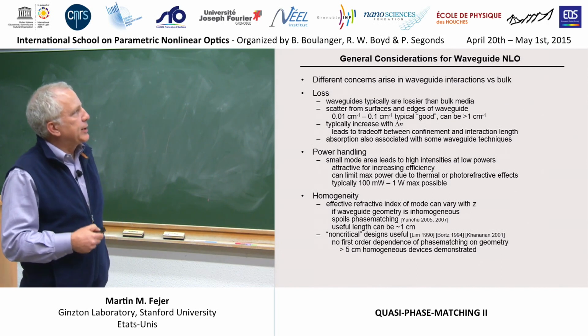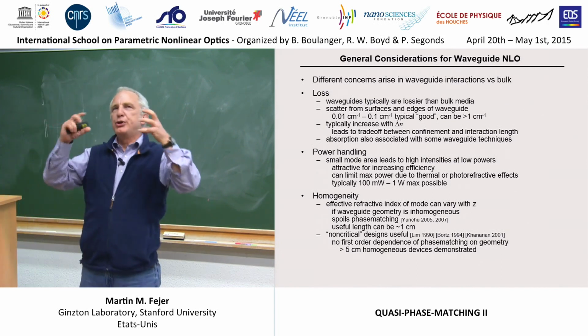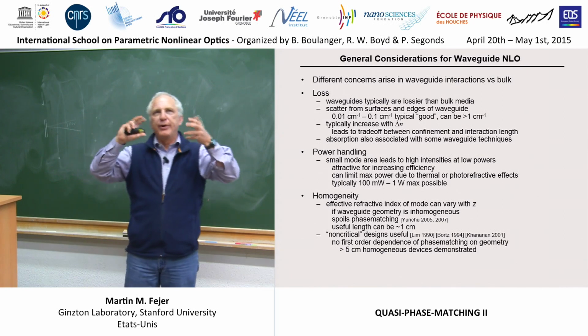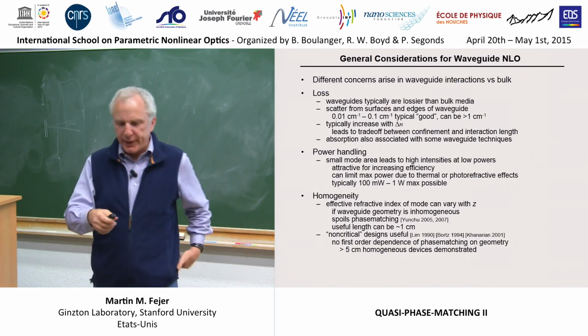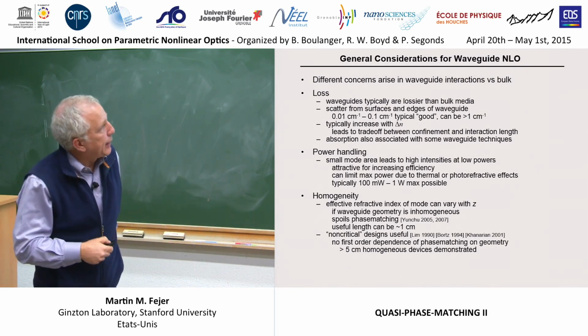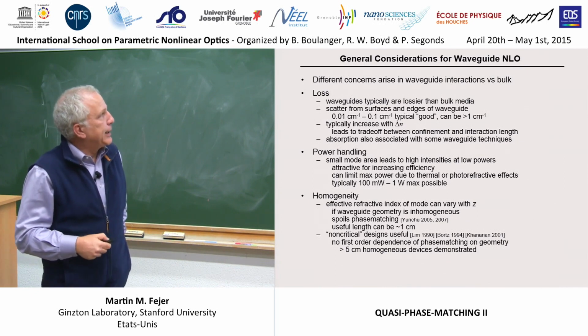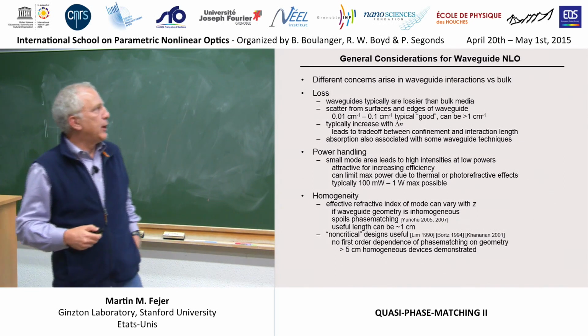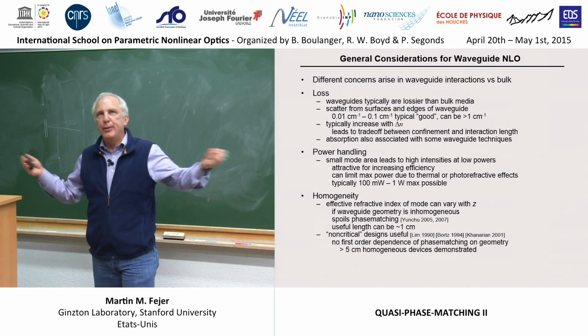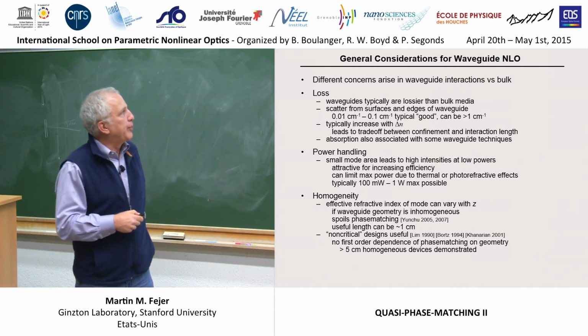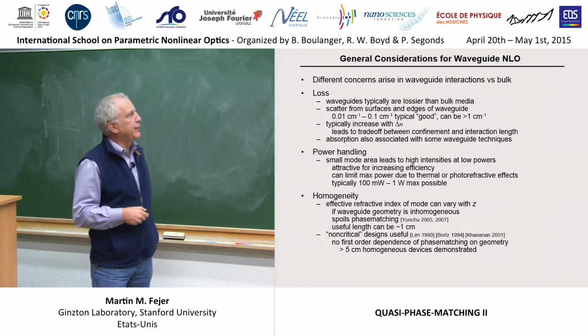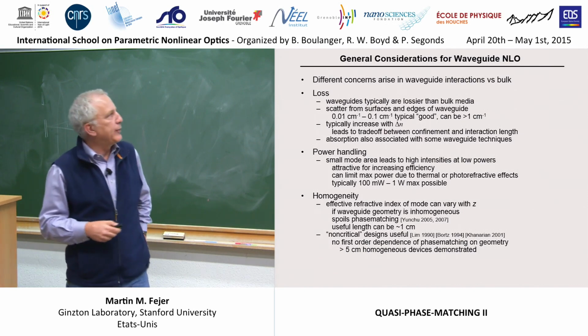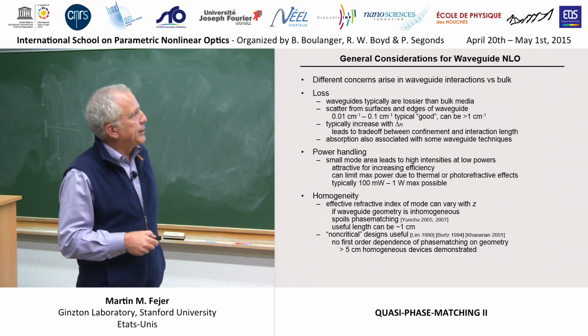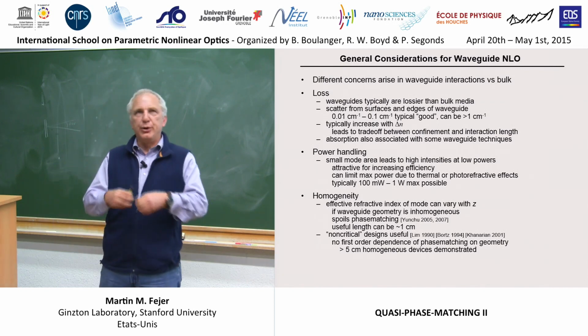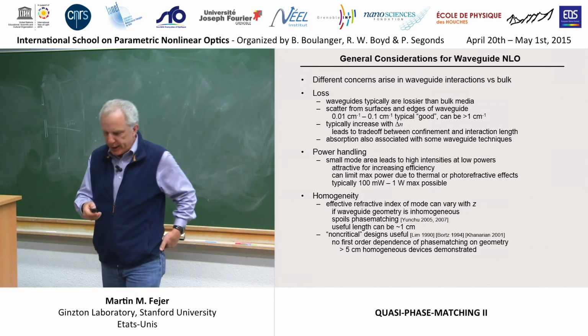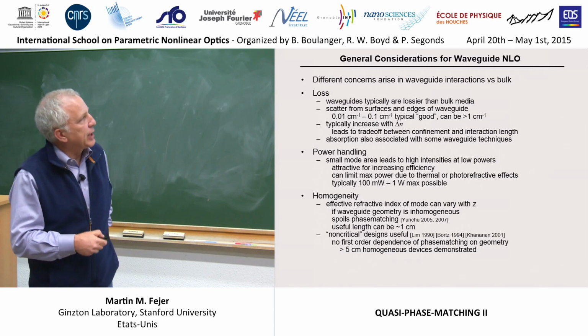One difference that's often quite important: while most bulk media have very low losses if they're a high quality nonlinear crystal, in waveguides it's rare to see losses much below 0.01 inverse centimeters—unless you've got a glass fiber or something. 0.1 inverse centimeters isn't rare, and waveguides in development or in complicated material systems can easily have in excess of an inverse centimeter of loss.